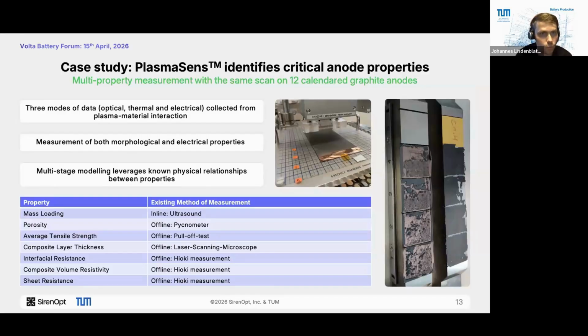We have multiple studies ongoing at the moment, including the use case we want to share today. The first thing we did is the multi-property measurement with graphite anodes. These are, of course, one of the easier samples, I would say. There, the three modes for the data, the optical, the thermal, and the electrical data, are collected with the plasma. We measured multiple properties offline, and one, the mass loading, inline, to actually label the data that we gather from our plasma sensor.